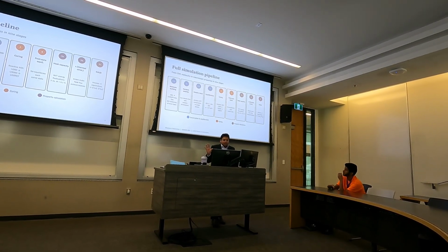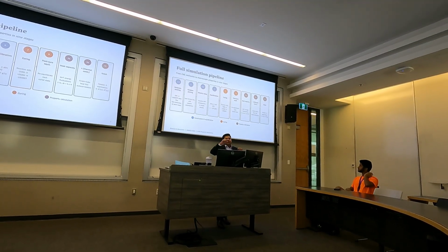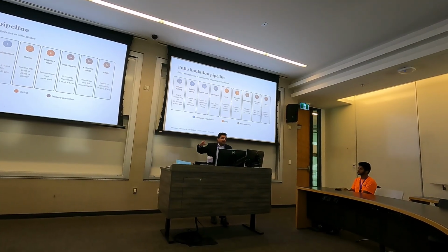This is the full simulation pipeline for the entire process that I'm describing today. It's bifurcated into 3 different stages: the construction and equilibration, curing, and property calculation. The construction phase that I mentioned before is basically the same one, with the stepwise compression, equilibration, and minimization, and then the curing process, where the first stage is the urethane reaction, and the second stage is the radical polymerization. After that we calculate the thermophysical properties and the viscoelastic properties.